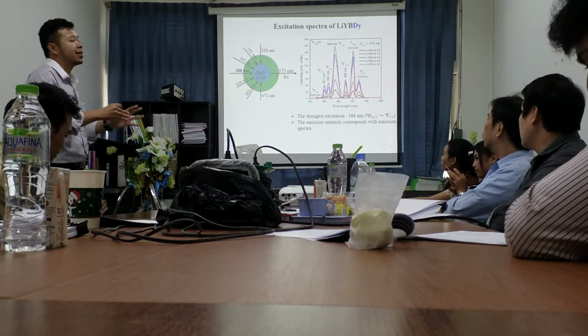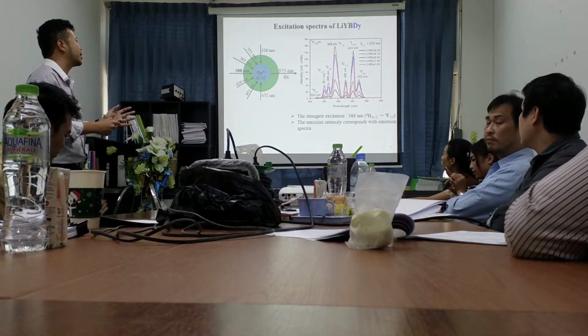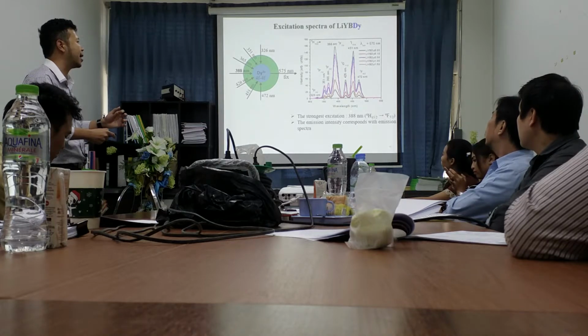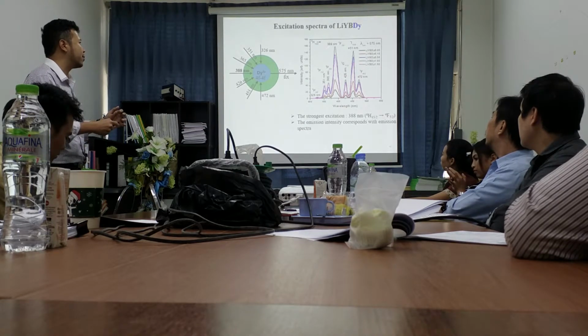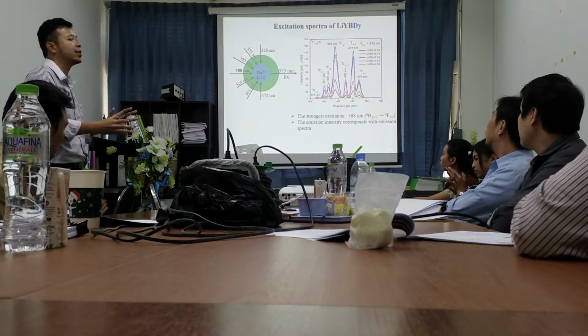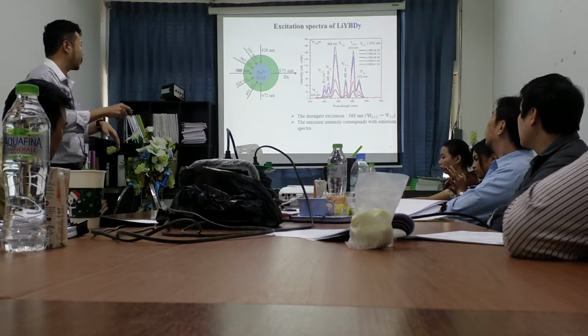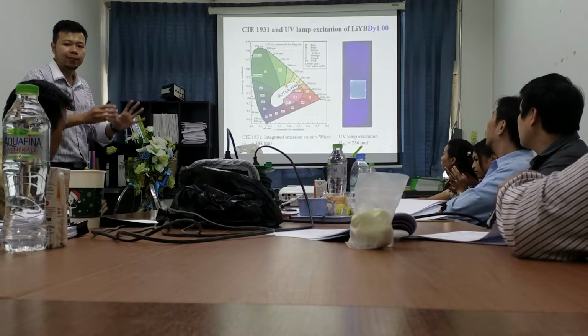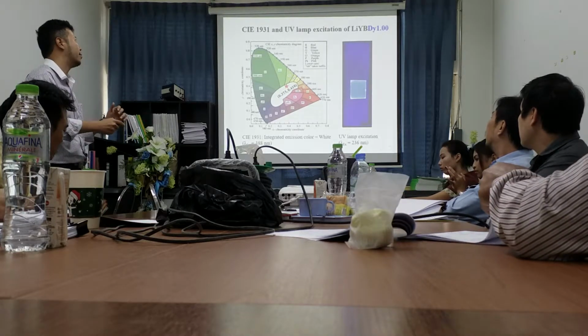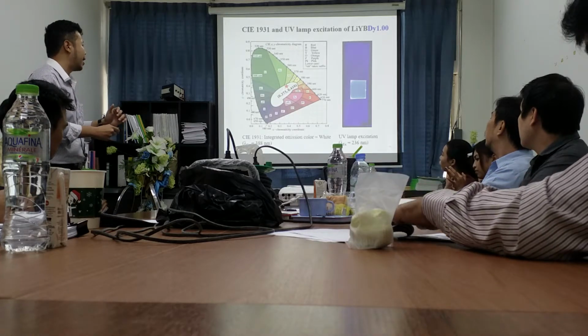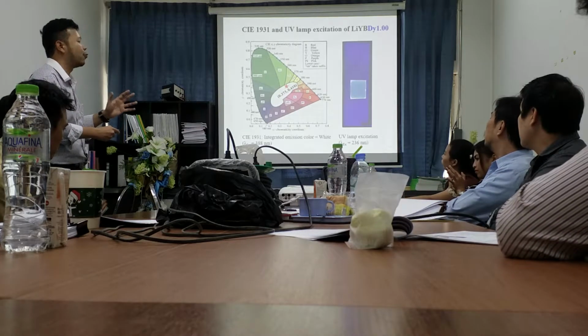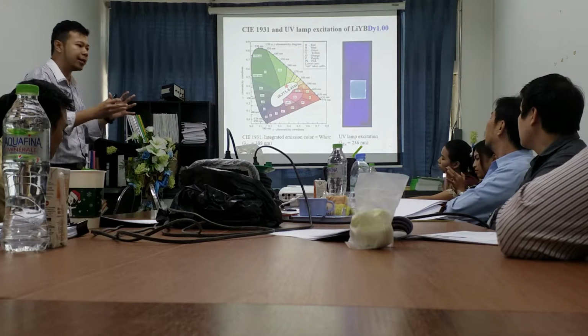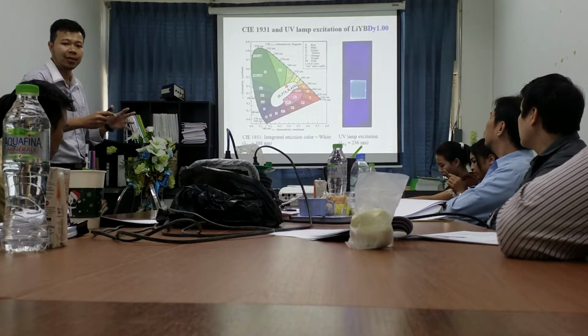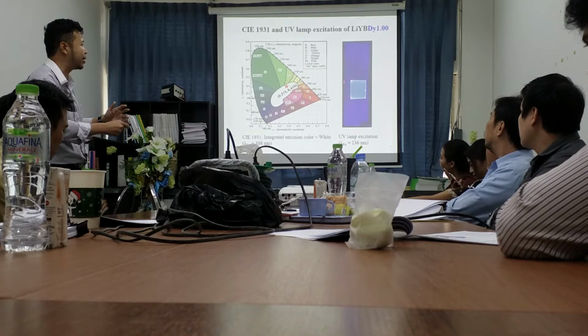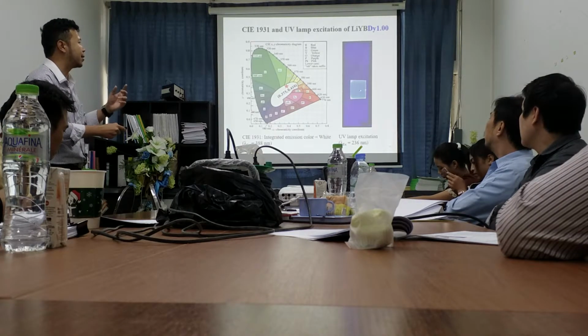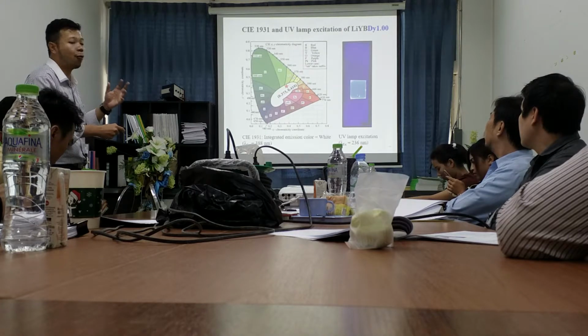To confirm the excitation wavelength, I measured the excitation spectrum and found the strongest excitation at 388 nanometers. This result corresponds with the emission spectra. I took the emission spectra to calculate the color coordinate by CIE1931 and found that the color coordinate is plotted in the white region. That means in theory, the glass performs white light emission. It's confirmed by UV lamp excitation. You can see this is the real picture, that the glass performs strong white light emitting.